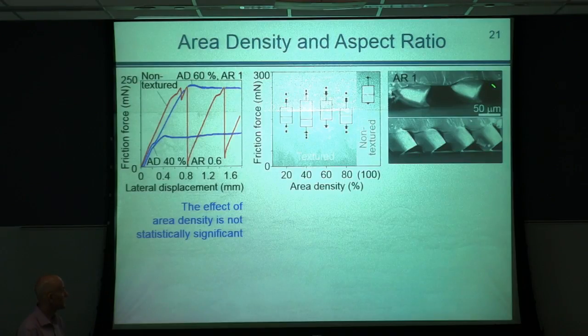So when we have different area density of the projections having the same aspect ratio, clearly the normal load is the same in both cases, which leads to higher deformation when we have fewer elements in contact, and they are tilted as a result of shear load. Then the contact area in both cases is more or less the same due to the same normal load that is applied when testing this property. And when contact area does not change, obviously this results in the same friction force.